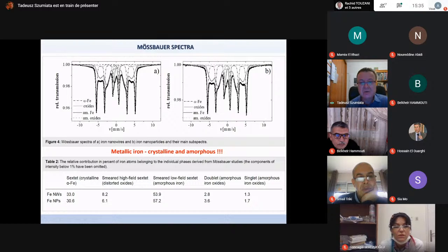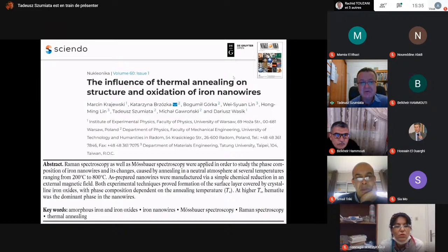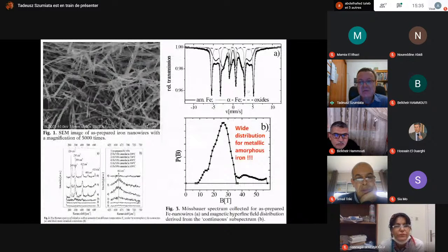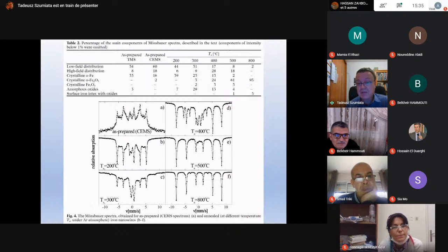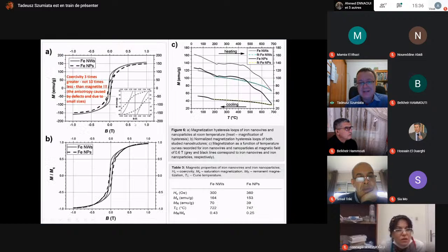broad structures. The same in the next paper, also from our laboratory, and we also see very broad structures. And here you can have directly plotted distribution of hyperfine magnetic field, very broad. So this result is confirmed both in the case of transmission Mössbauer spectrometry and conversion electron Mössbauer spectrometry. The spectra are very wide, but it is still only iron, nothing else.